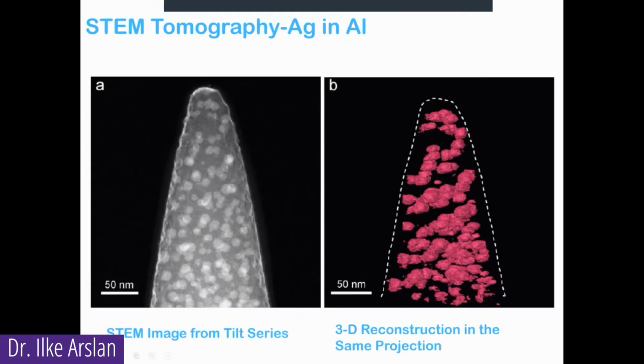And this was silver particles in an aluminum matrix. And I put this dotted line to show you where that aluminum matrix would be. These particles are just the silver particles that you see here. And this is an electron tomogram. So let's see if this movie works. Okay, so this is what the silver particles look like. We can't see the aluminum, obviously, it's just a light background, but you can see that these particles look elongated.